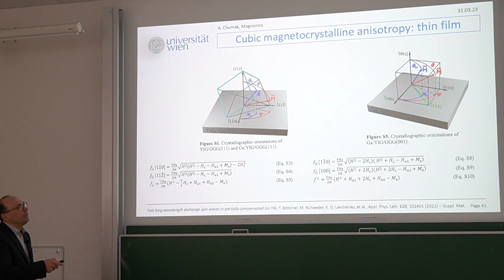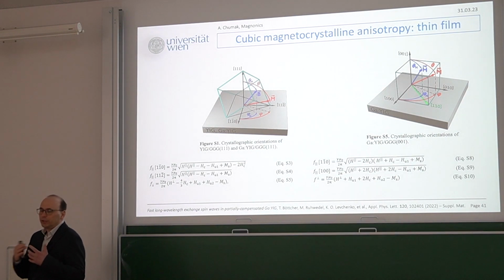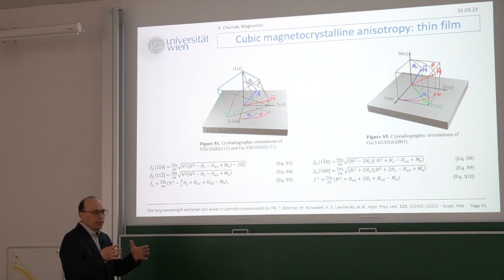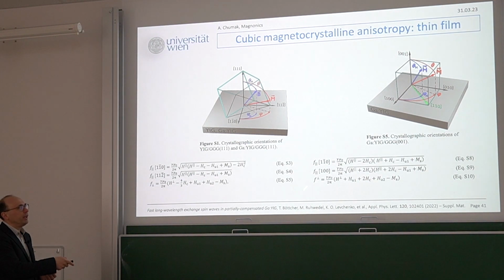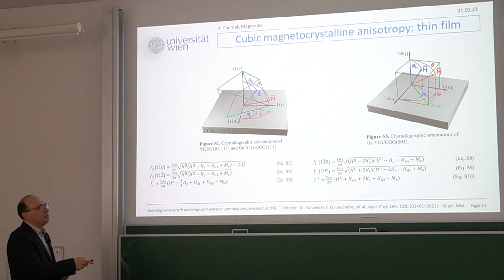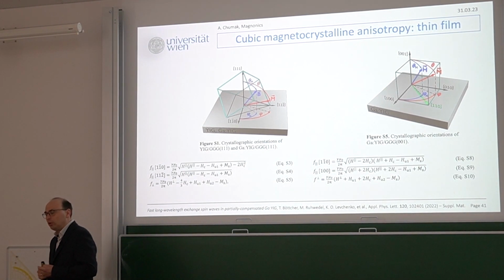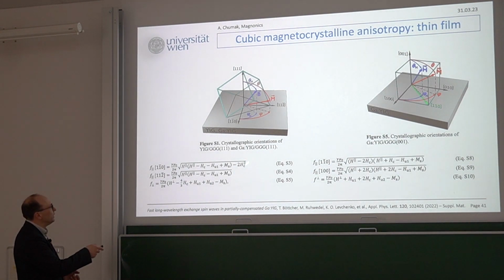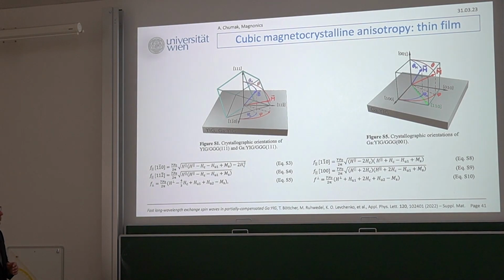But uniaxial anisotropy pretty often comes from a lattice mismatch between the material and the substrate, or from some other technological processes. For example, if the lattice slightly changes between gallium gadolinium garnet and YIG, then the crystal will be stretched or, vice versa, compressed very slightly, but this mechanical stress induces uniaxial anisotropy, which in some structures can be very big, often much bigger than cubic anisotropy, because yttrium iron garnet is a material with very small cubic anisotropy. It's one of the reasons why people like working with it: it has very weak anisotropy. And when you work with a 111 GGG substrate, its role, as you can see here, the H_C squared term is getting very small, so its role is getting even smaller. So much about cubic anisotropy.